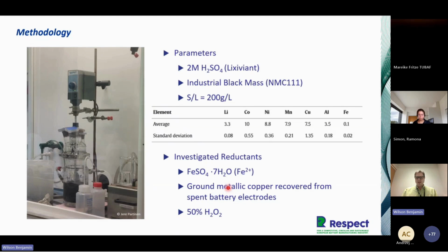The material itself had a combination of lithium, cobalt, nickel, manganese, but also copper, aluminium and iron. The last three particularly come from either the casings or the electrode materials, which are also within the battery elements, not just the active materials which contain the lithium, cobalt, nickel and manganese. So part of this was to look at the process as a whole, but to try and look at what difference the addition of reductants can make.